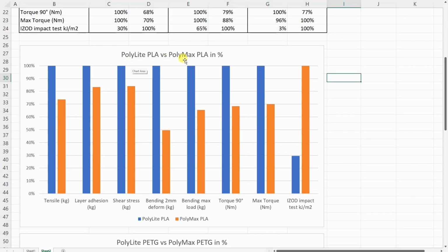This is the PolyLite PLA versus PolyMax PLA comparison in percentage, and we can see that the PolyLite PLA was stronger in mechanical tests compared to the PolyMax PLA. You can see the difference here in the graph, but on the IZOD impact test, the PolyMax PLA was, I know, 3 times stronger compared to the PolyLite PLA. So that's why it is important to understand this, so you can choose the correct material for your application. If you are expecting dynamic load impacts, the PolyMax PLA is better. But if you don't expect these dynamic loads, then for basically all other specifications the PolyLite PLA is better.